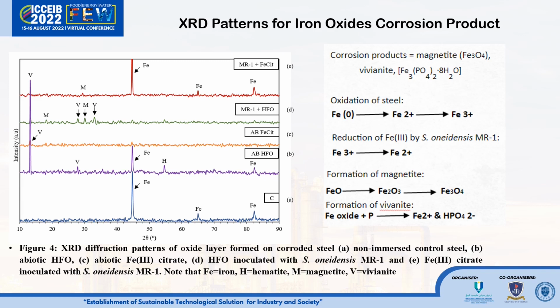To summarize, iron oxide treated with ferric citrate was incapable of being detected by the XRD detector because ferric citrate was rapidly solubilized and no crystalline phases could be formed in a certain period. But the dissolved iron 2 produced from insoluble HFO in the presence of Shewanella was associated simultaneously with the oxidation of steel, causing formation of other iron 3 compounds such as magnetite and vivianite by Shewanella.